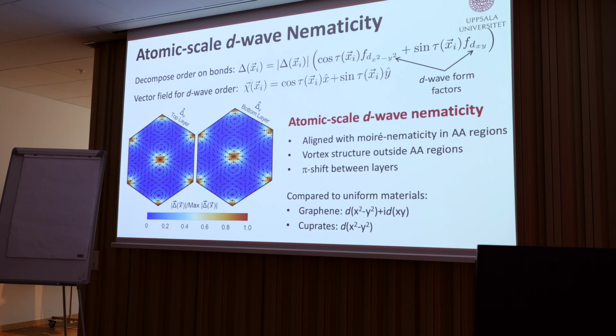So this is what we get on twisted bilayer graphene. And again, I would like to compare it with, if I did the same calculation on graphene, I would get the chiral d-wave state. And if I did it on a square lattice, I would get a nodal d-wave state. So in some sense, twisted bilayer graphene sort of does a little bit of everything. I get a real value d-wave order, but it can't decide which d-wave order it wants, so it sort of changes them throughout the unit cell.